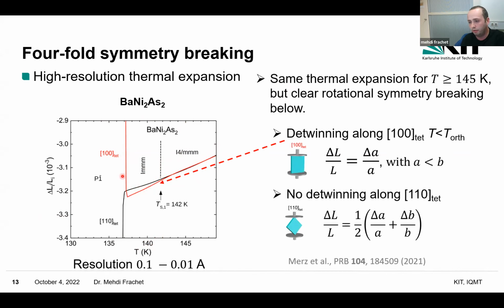So what actually occurs below 145 Kelvin in this orthorhombic state is that when the sample is aligned along the 100 axis, okay, using the thermal expansion setup, you apply a tiny force which allows to detwin the sample. So you measure the smaller in-plane axis. Now, when the sample is aligned along the 110 direction, you still measure a combination of the two in-plane directions. So there is no detwinning effect. Okay. So that's what occurs in this orthorhombic phase in thermal expansion.